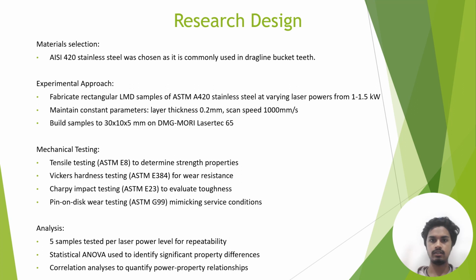as a shielding gas. A laser will be focusing on the substrate layers within a 2 mm diameter spot size at varying power levels. The layer thickness will be 0.2 mm and scan speed of 1000 mm per second based on the equipment's capabilities. Now some of the testing that we require is the tensile testing, which will follow ASTM